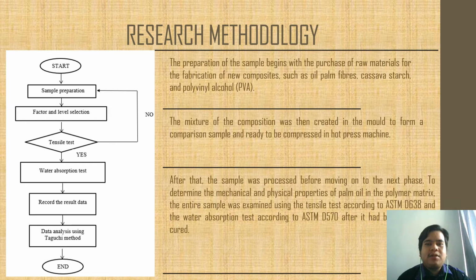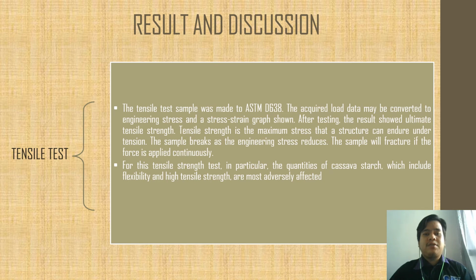After that, the sample was processed before moving on to the next phase, to determine the mechanical properties and physical properties of oil palm in the polymer matrix. The entire sample was examined using the tensile test according to ASTM D638 and the water absorption test according to ASTM D570 after it had been fully cured. After that, we can go through to the results and discussion of this project.